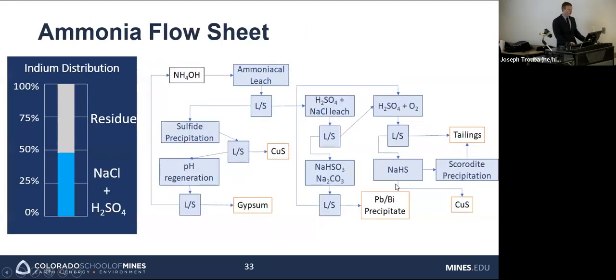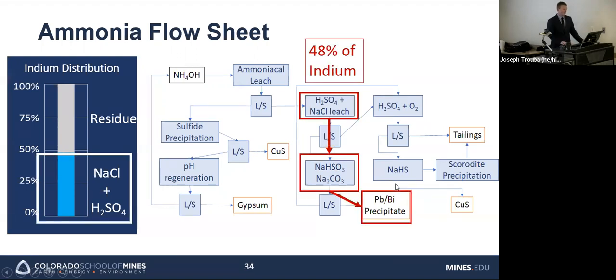Now let's look at ammonia. Following the ammonia leach, all of the indium reports to the solid because none is leached during the first stage. Then during sulfuric acid sodium chloride leaching, around 50% of indium is leached, which is then sent to a similar step to partial neutralization you saw previously.